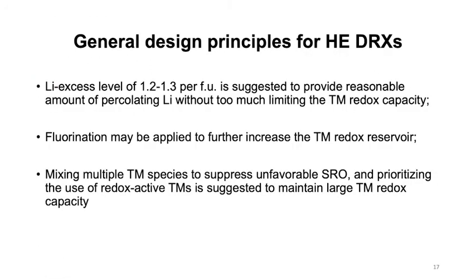Here we also outline a couple of suggested design principles for high entropy DRX cathodes. First, we would suggest applying a lithium excess level of around 1.2 or 1.3 formula units in order to provide enough percolating lithium, but without too much limiting the redox capacity on transition metal. And also, we may consider using fluorination to further increase the amount of transition metal redox reservoir. Regarding the choices of specific transition metal species, we would suggest prioritizing the use of redox active transition metals so that they can facilitate the lithium transport without sacrificing transition metal redox capacity.